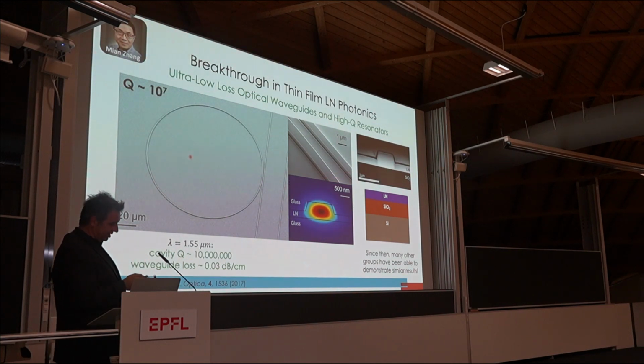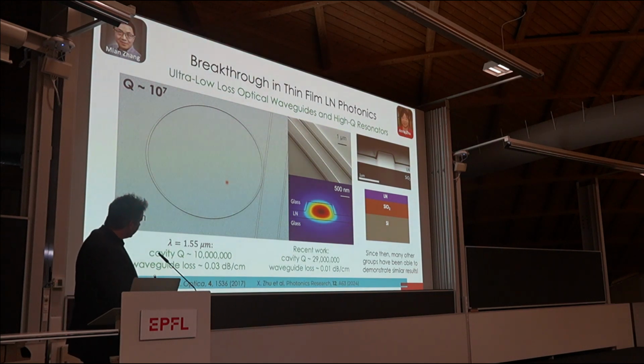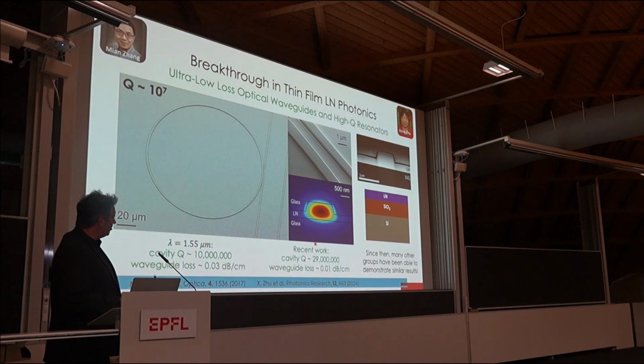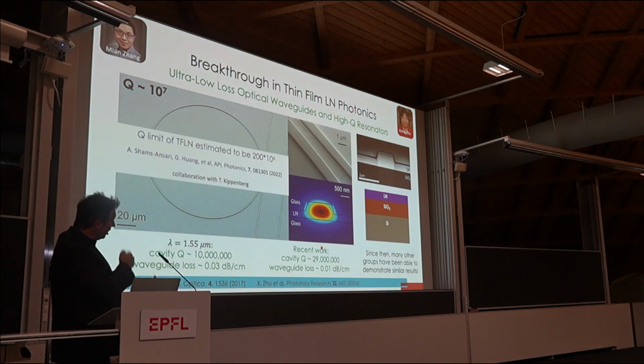The main reason why we were able to do this is because we had really high tolerance to pain from dealing with diamonds and etching diamond. And so we unleashed a lot of know-how that we had figured out then to make this happen. In more recent work in the group, we can go to 1 dB per meter, which is about 3 times better, which for many applications is good. And we also demonstrated that the limit of this platform is about another factor of 10. Beyond that, if you want a high Q, you need to either get better lithium niobate, or come up with better oxides possibly as well, and so on and so forth.